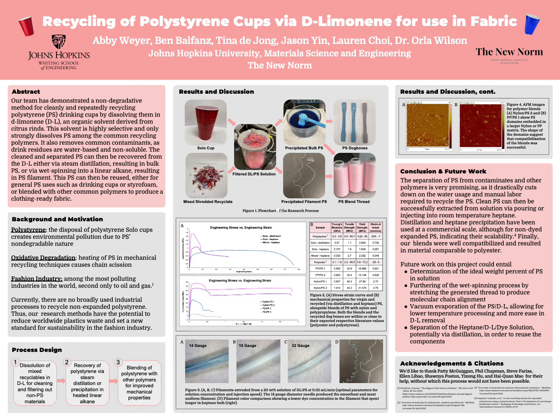For the recovered polystyrene dog bones, we found that the steam distillation was the least successful method since not enough D-limonene was extracted from the polystyrene. You can see the blue line of the top graph displays an elastomeric curve atypical of polystyrene. The heptane dog bone that went through the most heptane washes and longest drying time had mechanical values closest to that of polystyrene literature, indicating the best recovery.